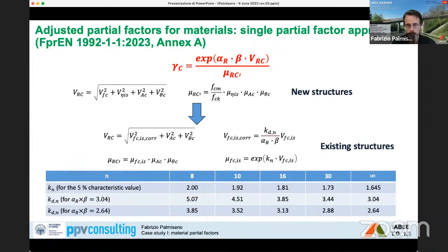modification is needed, and this modification will be included also in the second generation Eurocode 2. It will be a function of the sensitivity factor, the beta factor, and also of the number of test results, because we have to consider that if the number of test results is low, lower than 30, the random function to be assumed is more similar to a t-Student than to a log-normal function.